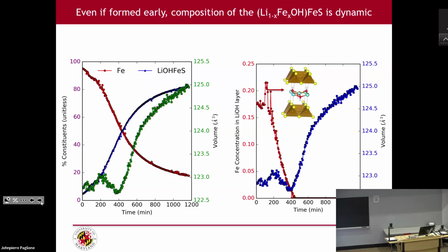And it has to do with the fact that under hydrothermal conditions, the ions are always sort of moving around. And so you have to take that into consideration. And so this is where you would get optimal superconductivity, about 20% charge doping into your iron selenide. And then once you lose it, you'll basically either kill it off or you come back to 8 Kelvin critical temperature.